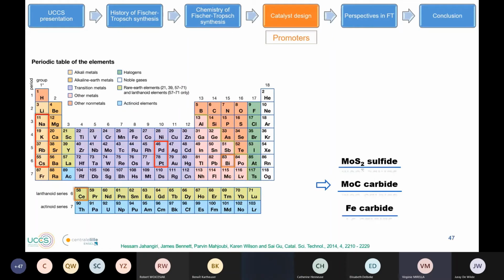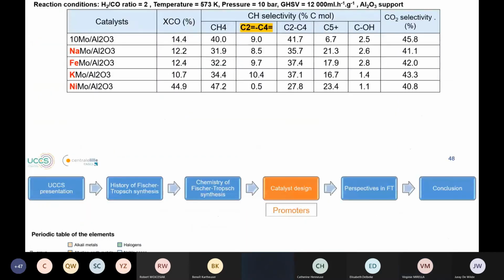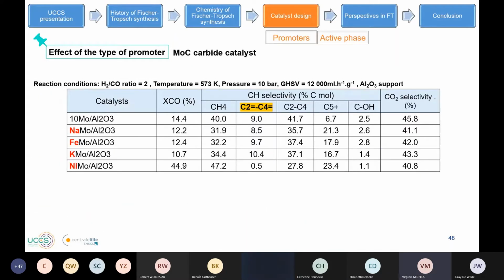Then now I'm going to tell you about the same story with molybdenum carbide catalyst. With molybdenum carbide catalyst, we also studied the effect of the type of promoter. We have studied molybdenum carbide catalyst with sodium, iron, potassium, and nickel. And when we observe the conversion of CO, we observe higher conversion with nickel catalyst. But when we have a look at the selectivity, with nickel catalyst, we have mainly selectivity to methane. That is not what we want.